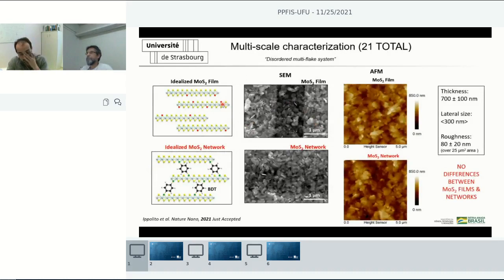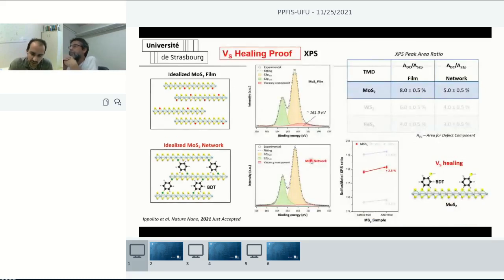Here is the scanning electron microscopy image of what we call film, which are the flakes together but no molecule, and what we call network, which is when the molecules are used to bridge these flakes. So we see no macro or micro differences, nor from AFM. Here we have films that are pretty thick, around 700 nanometers, and pretty rough. So we don't see any difference in this case between films and networks.